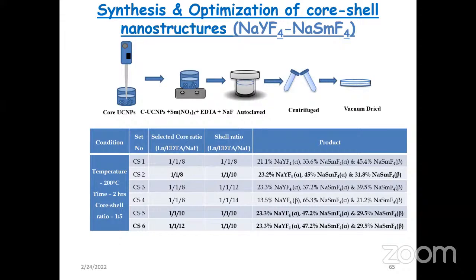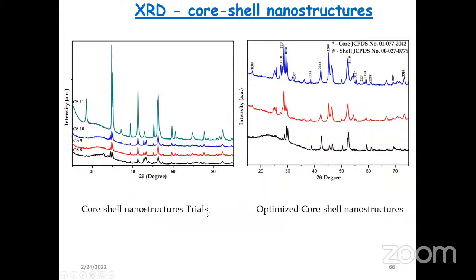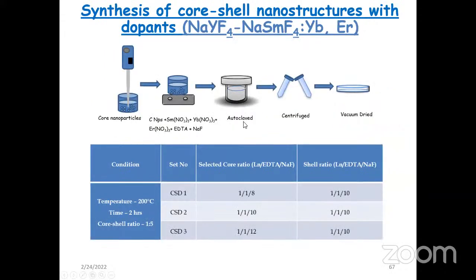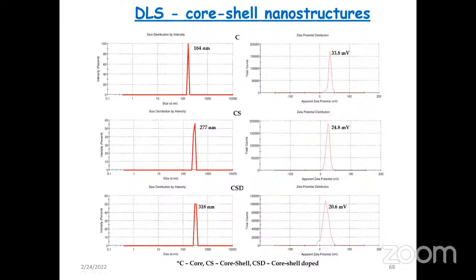So we have prepared core-shell nanoparticles by optimizing the concentrations. I'm not going into much detail. After making the core-shell nanoparticles, we also added dopants, erbium and ytterbium, which further enhance the photoluminescence activities. After making the core-shell nanoparticles with dopant, we did DLS studies. The core consists of 164 nanometers, whereas the core-shell is 277 nanometers, and the core-shell with dopant showed 318 nanometers.